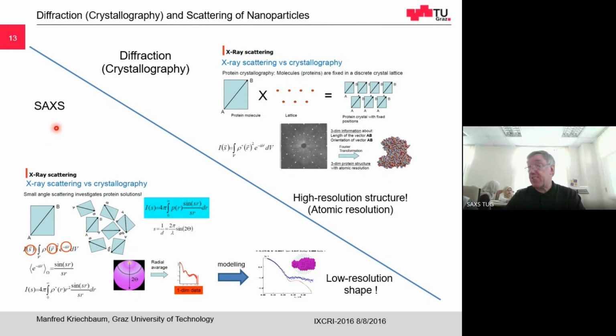In opposition, in SAXS, where you have your nanoparticle in solution, they adopt any conformation with respect to the X-ray beam. There's a spatial and temporal averaging of your nanoparticle. So you're losing the phase information. You only have the intensity information. And this gives you a diffuse scattering pattern, so no sharp single X-ray spots. And the result that you can get is a one-dimensional curve. And from that, you can only get the envelope shape of your nanoparticle, due to the loss of information, due to this spatial and temporal averaging of your structure. But on the other hand, you can investigate any sample in the natural environment, and you don't have to crystallize your sample.